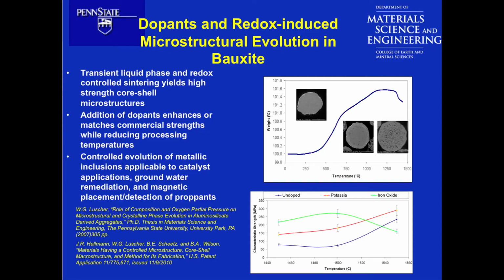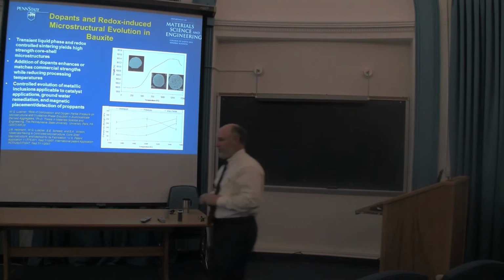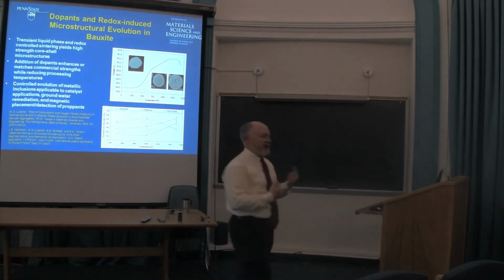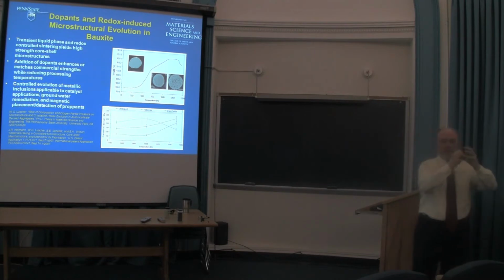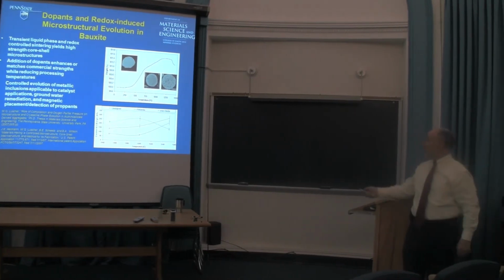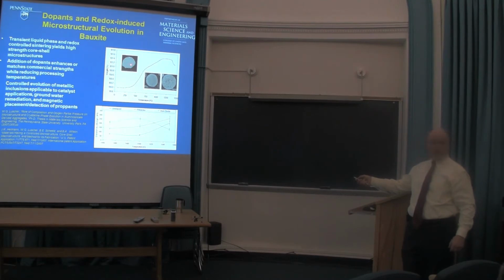but we came up with a few more surprises. This one blew us away. We should have known about it. All right? If you look at this microstructure right here, what you're looking at is one proppant particle that was sintered to full density, i.e. no porosity. And then by changing the oxygen fugacity, partial pressure in the sintering furnace, we re-evolved porosity. We decomposed the iron oxide to a different form of iron oxide of different valence state, giving off oxygen, which in turn crept the ceramic microstructure, leaving behind bubbles. This is a malted milk ball that started dense.